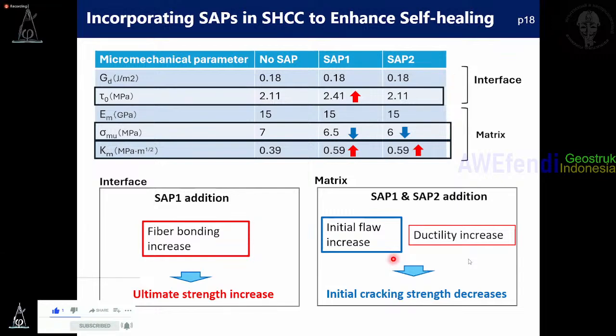And meanwhile, the interface may be enhanced because of the enhanced fiber bonding. So that means our analysis is relatively reasonable. Our assumption is reasonable. You add SAPs, you may have reduced cracking strength. But if you use it properly, you may have increased ductility.